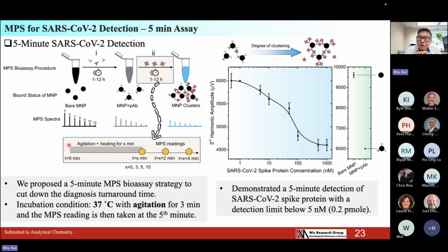So what we do is the first time we introduce 5 minutes bioassays on the MPS platform, which is the first report in the world that we can cut down the bioassay time from the sample loading to data reading. As you can see from the schematic imaging, we functionalize nanoparticle with the antibodies. So this will be the product as I highlighted in step number 2. This product will be the one the user will get. The user will get a small vial of nanoparticles, which is functionalized with antibodies. The user will add the samples, biofluid sample, into the nanoparticle vial.